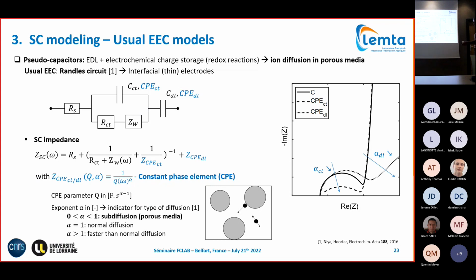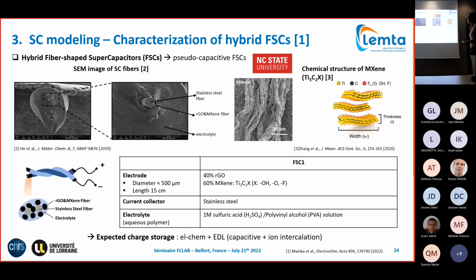And now the interesting case is if alpha is situated between 0 and 1, meaning you can measure the impact of the pore space on your ion diffusion. The lower alpha means that the pore size is lower than the free path of your ions, meaning you have really sub-diffusion, a big impact on diffusion. Okay, so that would be used as well.